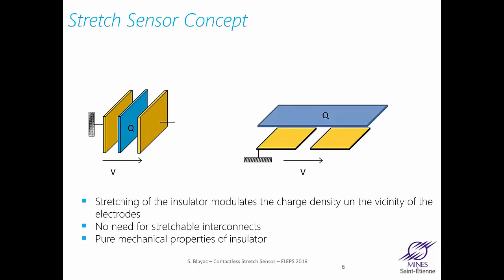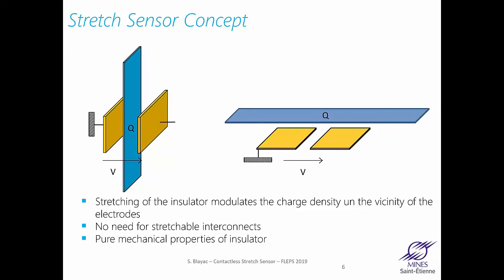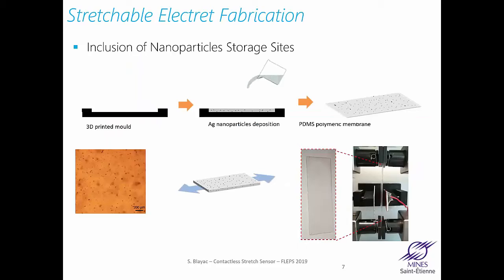So the stretch sensor concept is the following. We just use stretchable materials as an insulator between two electrodes. There are two possibilities of integration. Either you can sandwich this electrode between the two electrodes, or have a planar structure like this. And then you have a certain charge in the insulator, and if you stretch the material, then you will modulate the charge density and obtain a voltage variation. That's what we are investigating for designing our sensor. So to fabricate this material, we start from PDMS films. We integrate some charges, some nanoparticles in it, and then we are able to put it in a stretching machine here and make the test of what we can do with it.